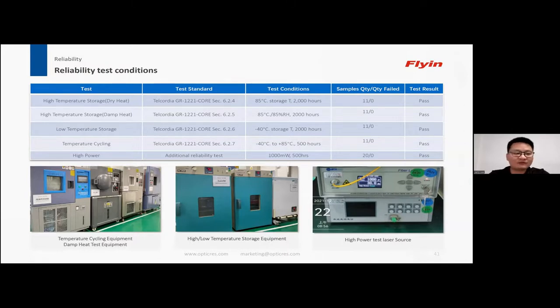Generally speaking, we have 4 conditions that need to be tested, but you can see the fifth line, high power. High power is an additional test condition we have at Flyin only. This is not included in the Telcordia GR standard. And for the reliability test, normally we take the Telcordia GR-1221-CORE standard as our testing standard. So let's have a look at the details. First line is about high temperature storage. This is a dry heat. That means the temperature is 85 degrees centigrade. We don't define the humidity. This takes up to 2,000 hours for test.